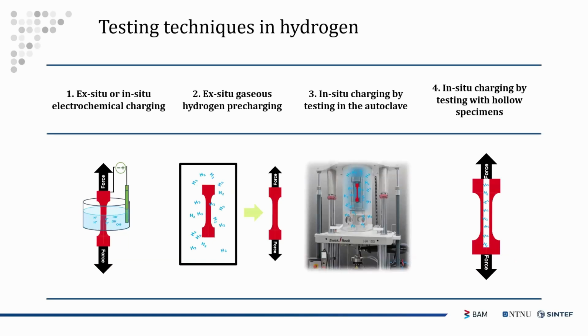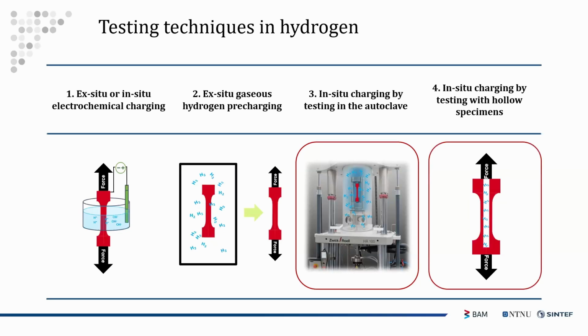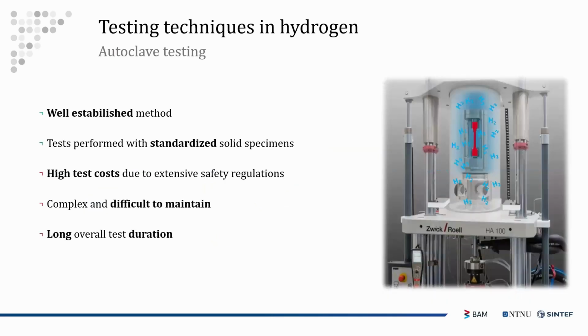So in order to test the effect of hydrogen environments on the materials, we have several techniques. They could be either ex situ or in situ testing. But when it comes to ferritic steels, we basically rely on in situ testing, charging with gaseous hydrogen in order to mimic the actual environmental condition of a pipeline. And we can use either an autoclave filled with high pressure hydrogen or a more, let's say, novel and unconventional technique that consists of using a hollow specimen as a containment volume for pressurized hydrogen. I will not go in depth because it has already been explained, but I will briefly summarize some advantages of the first technique and the second one.